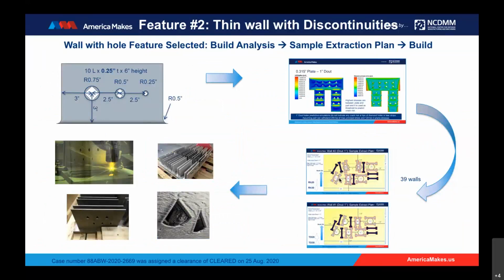Right. So similar to feature one, we followed the process of coming up with a design for the thin wall with discontinuity, which we've analyzed using simulation to avoid interactions between neighboring features inside the wall. Meaning, if there were two holes next to each other, we didn't want the building of one feature to influence the other. After doing that simulation, we've come up with tensile specimen extraction plans, and then we've proceeded to fabricating these walls.